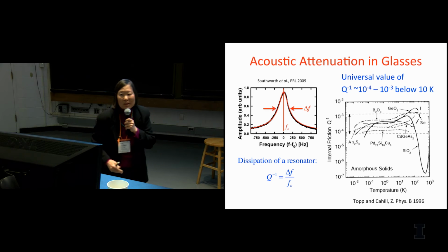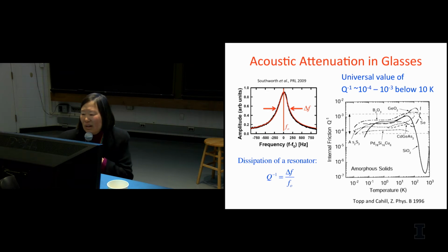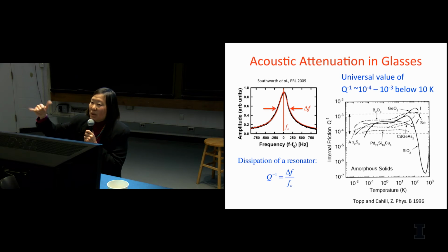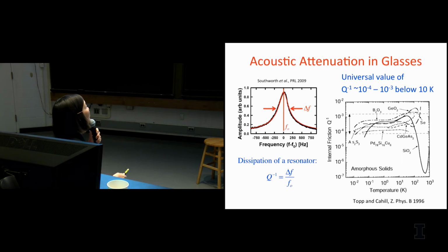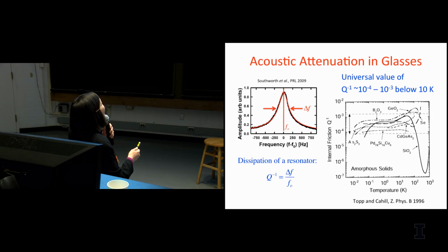If you take the glass, you put it on some sort of oscillator, like a double paddle oscillator, you wiggle it back and forth, you'll find some resonant frequency, f naught, and some line width. So this is amplitude versus frequency, and you get some line width. That line width is a measure of the dissipation of that oscillator. So Q inverse is the line width divided by the resonant frequency. And if you look at Q inverse on a log scale versus temperature on a log scale, for a variety of glasses, you get things within the range of 10 to the minus 4, 10 to the minus 3. What picks out that value?